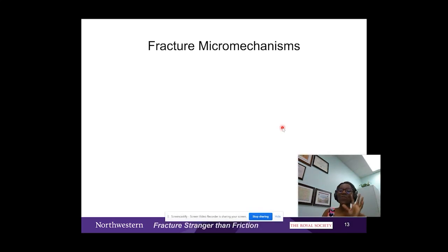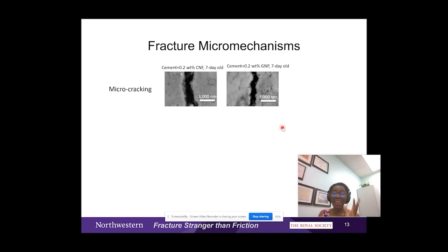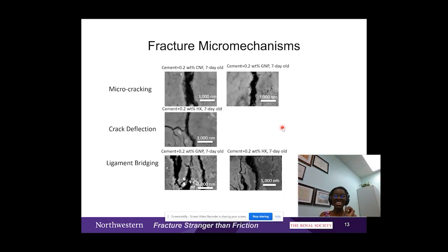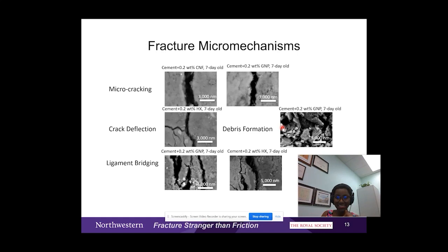I identified 4 types of fracture micromechanisms: microcracking, crack deflection, ligament bridging, and debris formation. We can even see the thickness, in this case, or the width of the crack during the fracture, and it is between 1,000 to 2,000 nanometers.